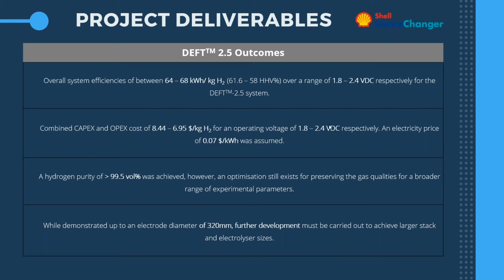And in terms of achieving the gas purities, we had to achieve anything in the region of 99.5 volume percent and higher, which is great because we managed to achieve that with a membraneless principle, and we've demonstrated that we are able to go about achieving good gas purities, very similar to what you get from a conventional alkaline electrolyzer. And in terms of scale up, previously we started very small, but with our game changer unit, we're able to provide a demonstration in the region of 320 millimeters in size.